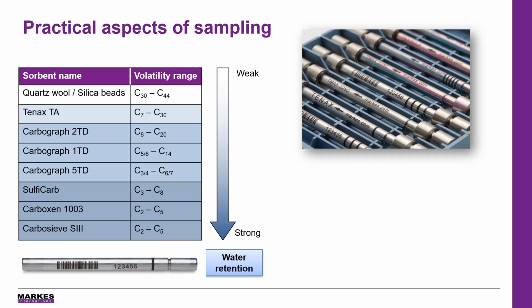A critical consideration of any TD analysis are the sorbents used for capturing these volatiles from our test samples, and these can vary depending on what volatiles we're analysing. Very volatile organic compounds require strong sorbents to retain them, whereas the semi-volatile organic compounds can be retained by weaker sorbents. Typically, we have a variety of volatiles that we want to analyse from a sample, so then we need to use multiple sorbents within our sorbent tube to capture this full range. These multi-bed sorbent tubes are also ideal if you're not really sure what volatiles you're expecting from your sample.